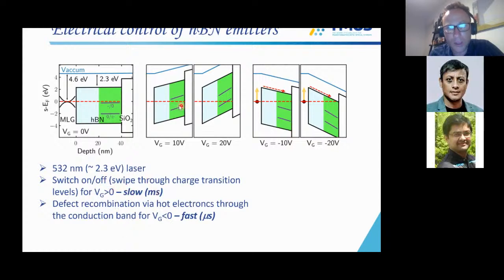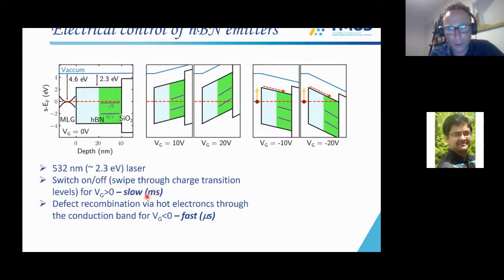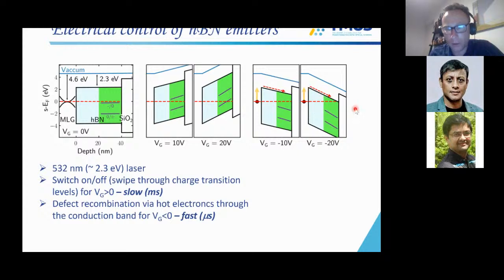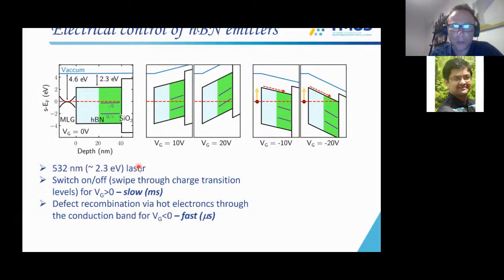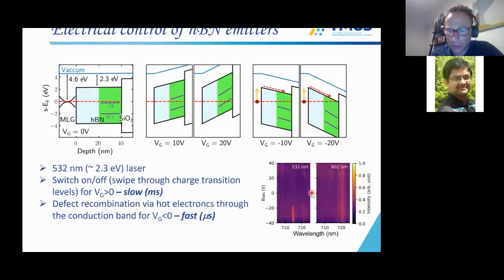So of course, this defect-induced luminescence will be very slow, and these fast electrons or hot electrons will be very fast, exactly as we see in our rates that I showed you a slide ago. And the second proof is, of course, if we now turn the excitation wavelength to 600 nanometers, so much lower than 2.3 eV, we're not going to see any of these defects. And so we did exactly that, and we see exactly that.